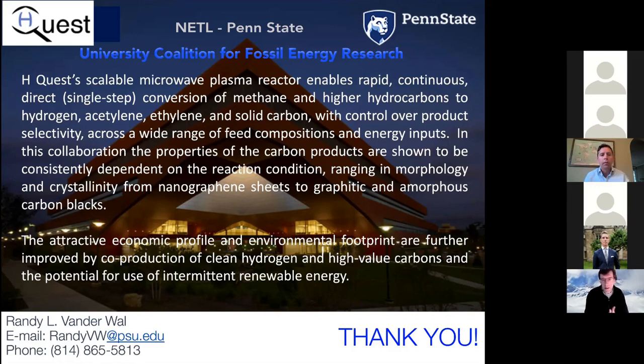And so you're exactly right. I think the pandemic problem, sorry for the word, but the universal problem, I just had to do that, the universal problem with quartz tubes as a reactor confinement, even given the microwave transparency, is in fact at some point with hydrocarbons, you'll wind up with some carbon deposition, and then it becomes a susceptor, local heating of the quartz, it'll blow a hole in the wall. This reactor, as I showed on the earlier slide, is an all metal cavity design. There is no quartz. It's an all metal cavity and far larger than the usual diameter for quartz tubes at laboratory scale. So there is not a carbon coating, carbon deposition. And even then again, it's a metal reactor. They do have the capability for different gas injections in terms of co-feed or supplementary feed somewhere within the plasma, or even other fluidized type bed arrangements as well. So it's a much larger scale, somewhat free from those other encumbrances as often encountered.